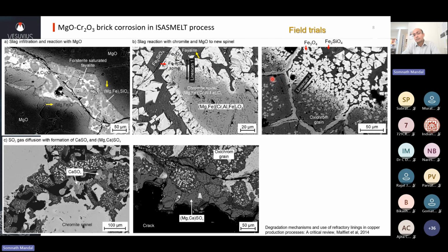And then you see a fused magnesia-chrome grain. This microstructure is very typical of a fused magnesia-chrome grain. And you see that these fused magnesia-chrome grains are slowly dissolving out into the slag as Fe3O4 or magnetite spinel crystals. This is an inverse spinel.